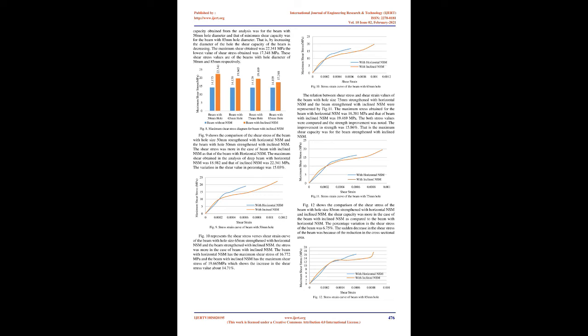The maximum shear capacity obtained from the analysis was for the beam with 50 mm hole diameter, and the minimum shear capacity was for the beam with 85 mm hole diameter. That is, by increasing the diameter of the hole, the shear capacity of the beam is decreasing. The maximum shear obtained was 22.341 MPa. The lowest value of shear stress obtained was 17.348 MPa. These shear stress values are of the beams with hole diameters of 50 mm and 85 mm respectively.